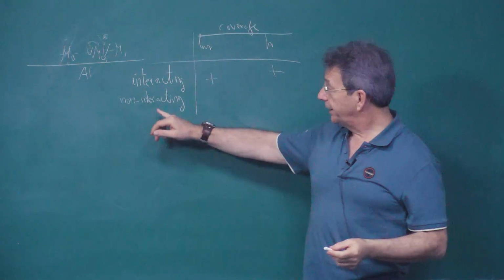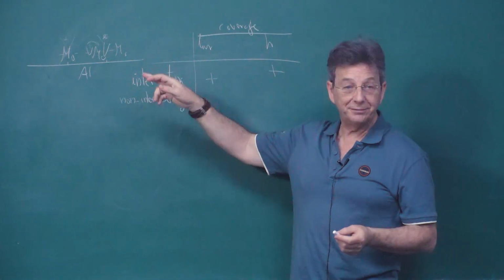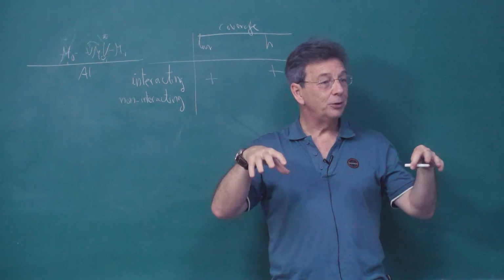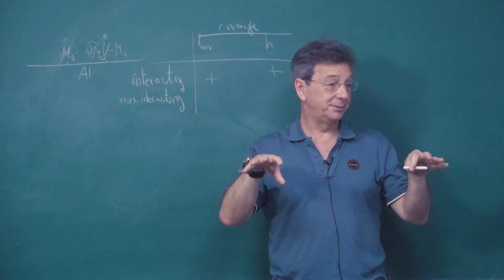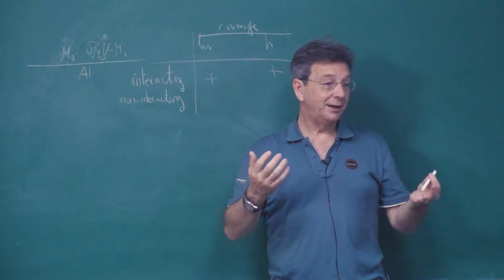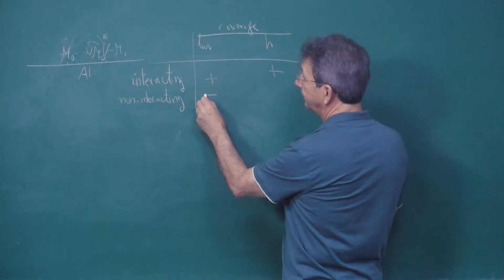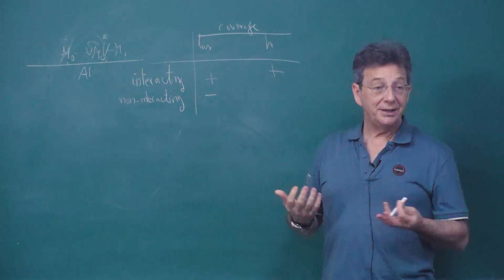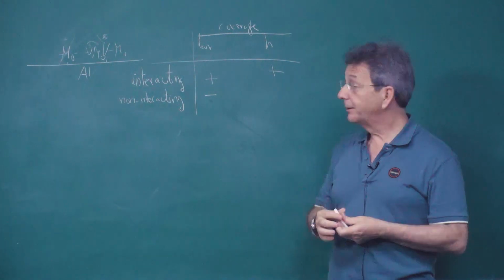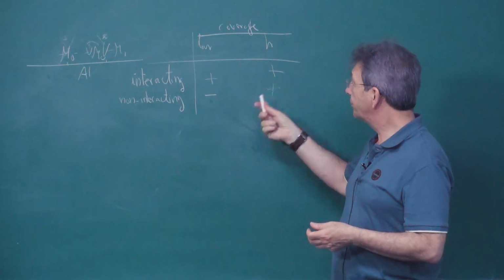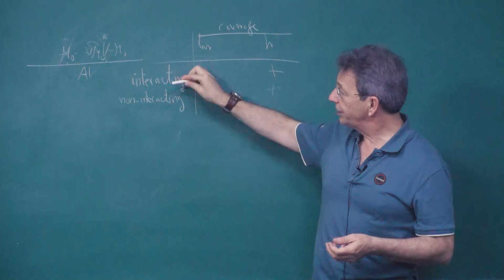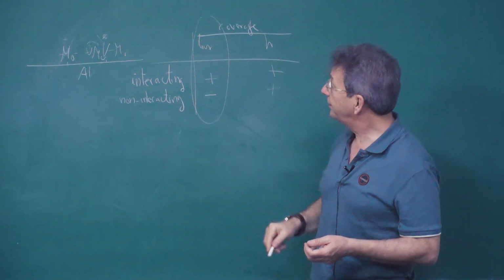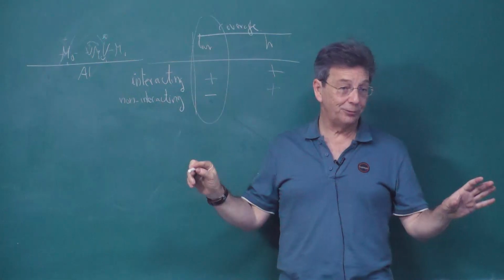Those that you consider non-interacting can be, for instance, molybdenum and vanadium. At low coverage, if there is space for both of them, they will be sitting nearby, they will not really interact, and each one will be doing its job. So somehow it's like they don't interact between each other. So this is non-interacting. So at low coverage, they don't interact. At high coverage, above the monolayer, in the end, they will make something because there is not space for all of them together. So in such a case, they will interact. So somehow, whether I define those additives or two components as interacting or non-interacting is because of the way they interact with each other at low coverage, when there is space for both of them.